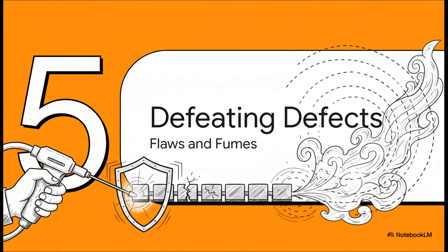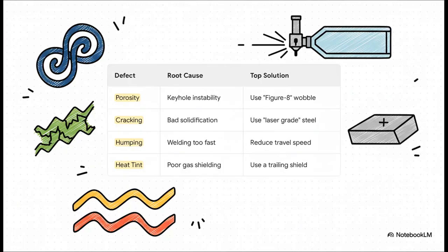But the battle isn't over. Now you have to fight a war on two fronts: defeating the defects that can scrap your expensive part and protecting yourself from the invisible dangers of the process itself. Think of this as your field guide for that war. Got porosity, those little bubbles in the weld? Your keyhole is probably unstable. Use a figure-8 wobble to stir it up and let the gas escape.